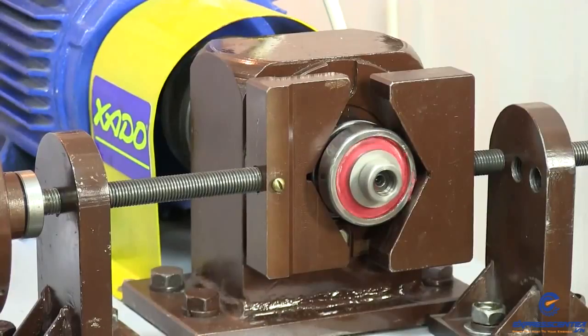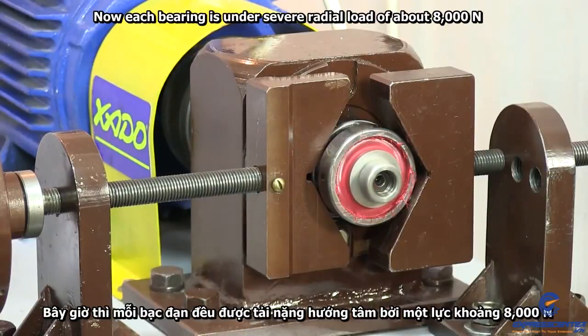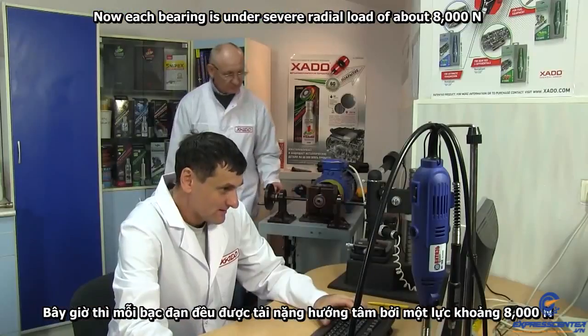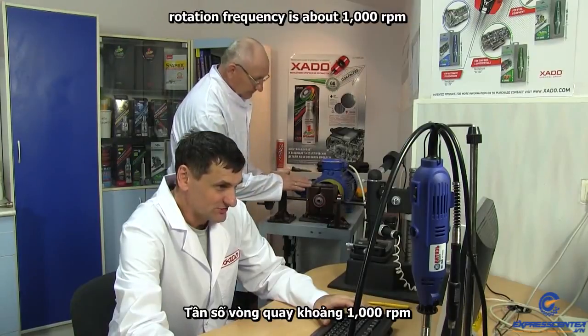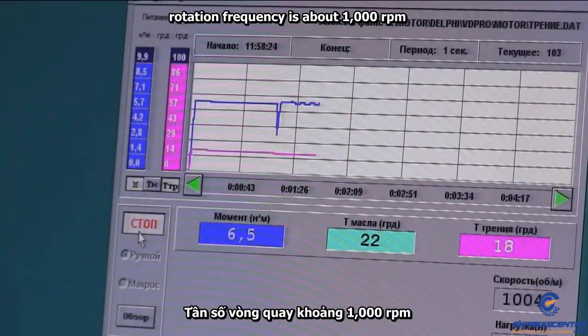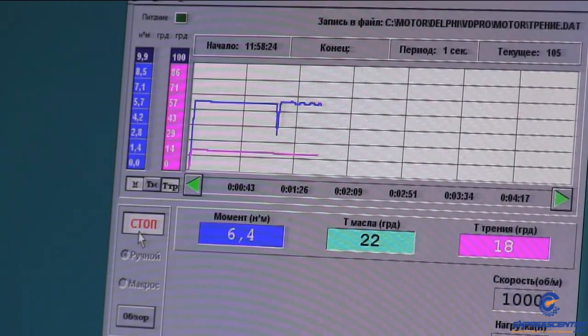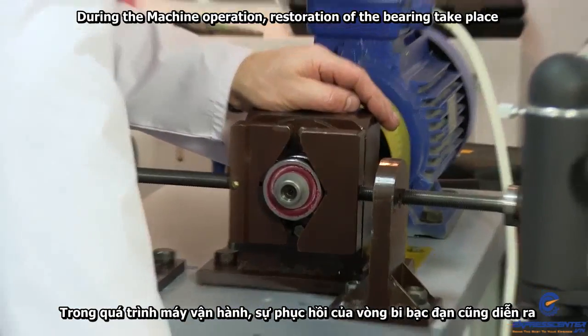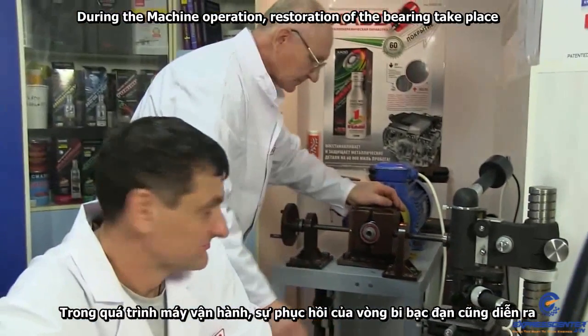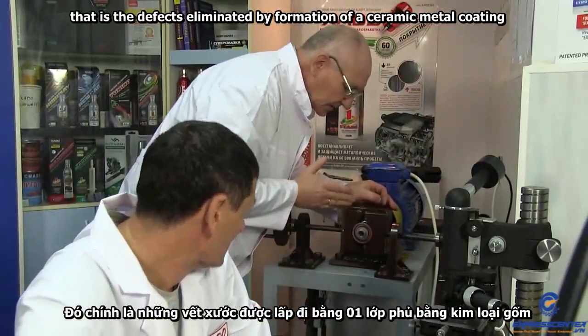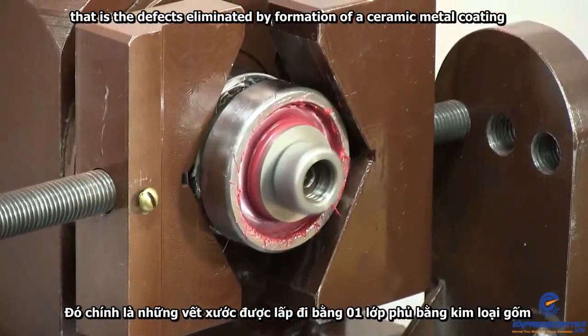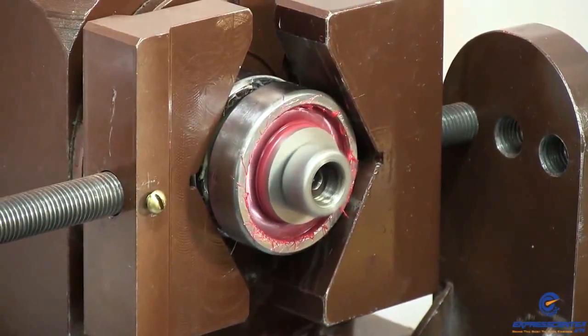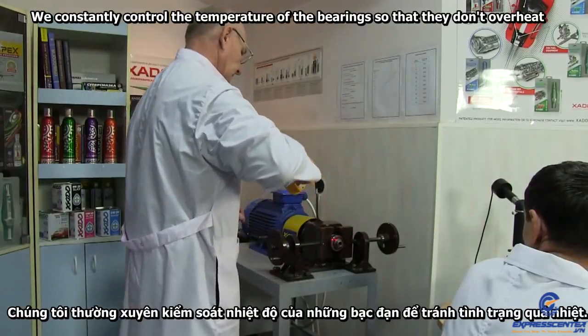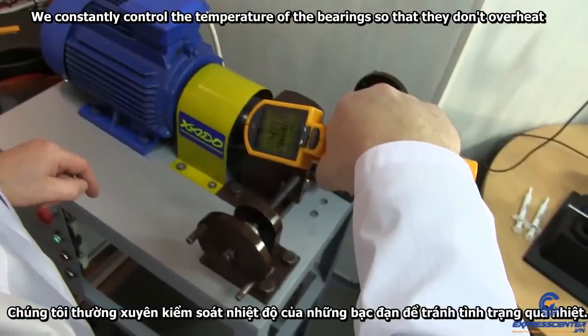Let's start the machine. Now each bearing is under severe radial load of about 8,000 N. Rotation frequency is about 1,000 RPM. During the machine operation, restoration of the bearing takes place. That is, the defect is eliminated by formation of a ceramic metal coating. We constantly control the temperature of the bearings so that they don't overheat.